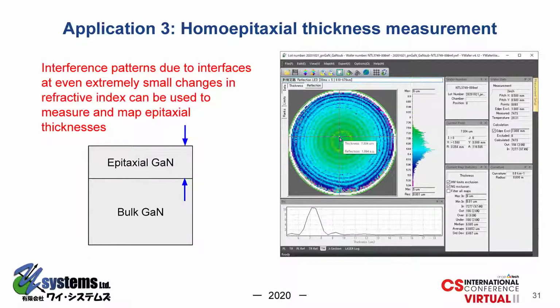Epitaxial layer thickness. The application of reflection and/or transmission mapping gives surprisingly accurate epitaxial layer thicknesses, even in the case of homoepitaxial, where theoretically the material should not have any optical interface, as shown here.